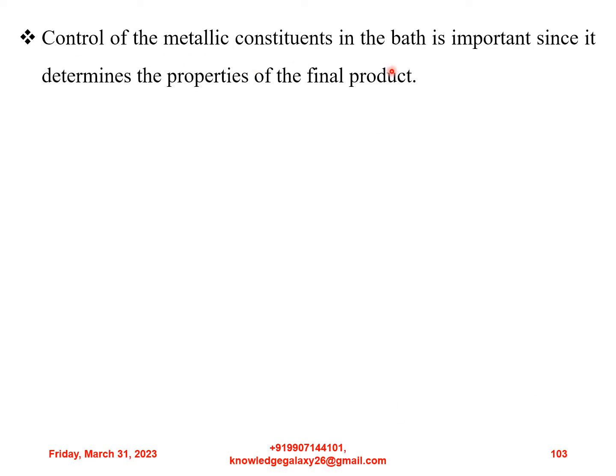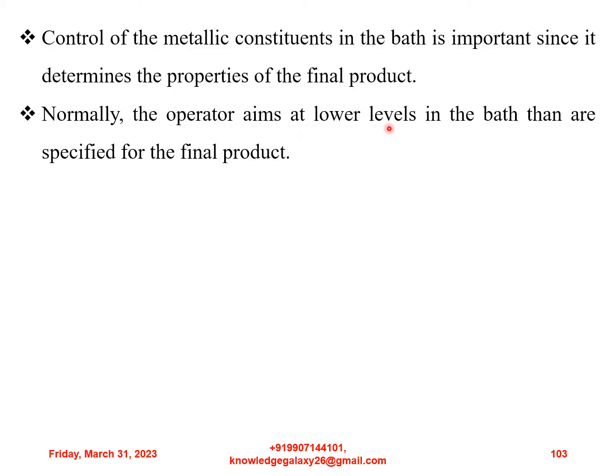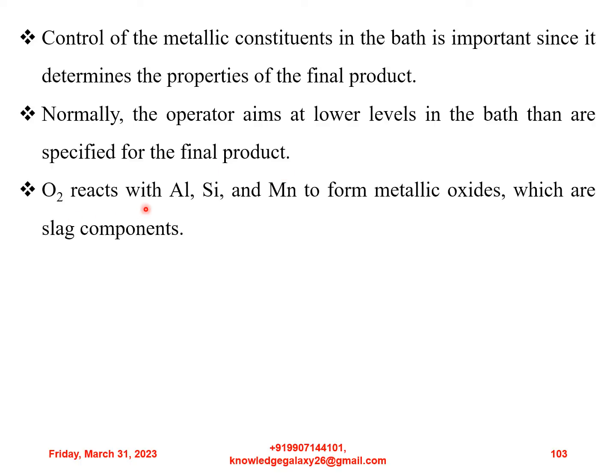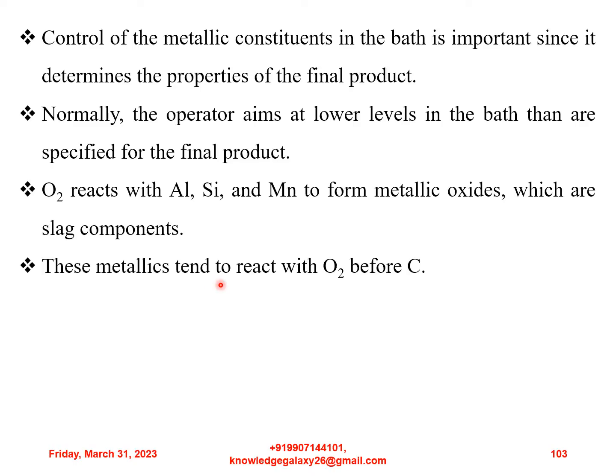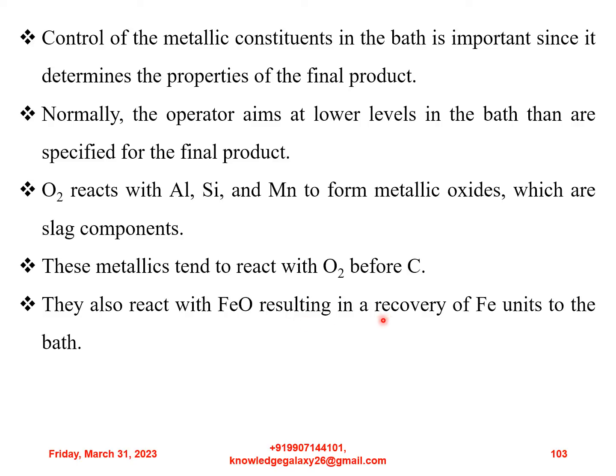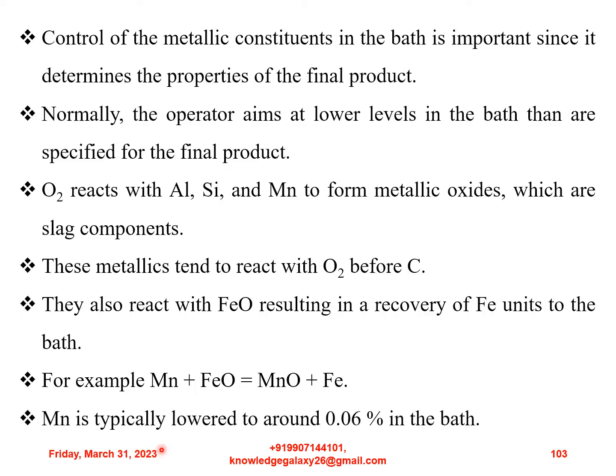Control of the metallic constituents in the bath is important since it determines the properties of the final product. Normally, the operator aims at lower levels in the bath than are specified for the final product. Oxygen reacts with aluminium, silicon and manganese to form metallic oxides which are slag components. These metallics tend to react with oxygen before carbon. They also react with FeO resulting in a recovery of iron units to the bath. For example, Mn plus FeO gives MnO plus Fe. Manganese is typically lowered to around 0.06% in the bath.